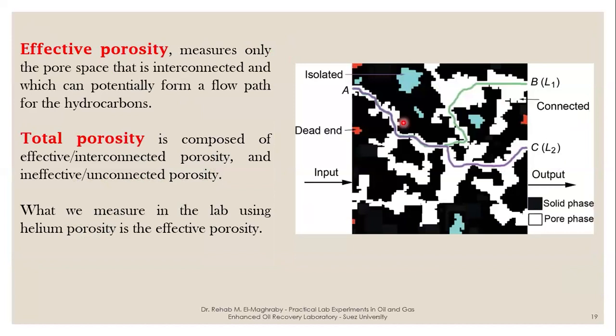If a pore is connected, it is called effective porosity. This means that once the oil or the water or the gas comes in, it can come out. But if it is isolated, what is in will remain in as long as the core is not touched. This is connected pores. This is isolated, isolated, isolated. So can I measure the amount of isolated pores? Actually, yes, I have to crush the core. So now it is a destructive test. I destroy this core plug, it will no longer be in use, and I can no longer use this core again because it will not be the same shape.